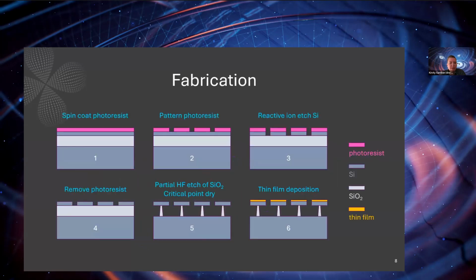So I fabricate these in-house at the clean room at the Quantum Matter Institute. We start off with a standard silicon on insulator wafer, and we spin coat photoresist onto the top of that. And then we use optical lithography to pattern the photoresist. So we basically write into the photoresist and create the shape of the microdisc, the micro resonator that we want to produce. We then use reactive ion etching to transfer the pattern from the photoresist into the silicon layer. And at that point, the photoresist has done its job, so we can remove it.